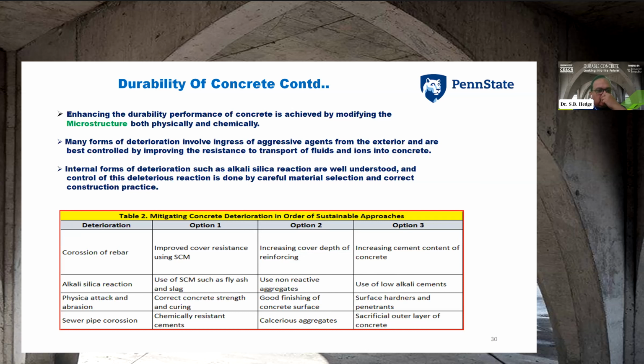So various deterioration processes are happening, for example, the corrosion of rebar, alkali silica reaction, physical attack and abrasion, sewer pipe corrosion, etc. The three options which I mentioned here: option 1 is improved corrosion resistance using SCM, use of SCM such as fly ash, correct concrete strength and curing. Option 2 is increasing cover depth of reinforcing, use of non-reactive aggregates, good finishing of the concrete surface. Option 3 is increasing cement content of concrete, use of low alkali cements, surface hardeners and penetrants, etc.